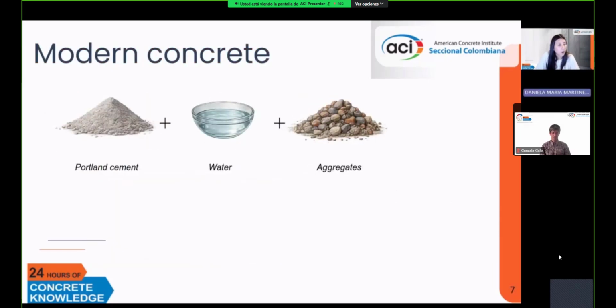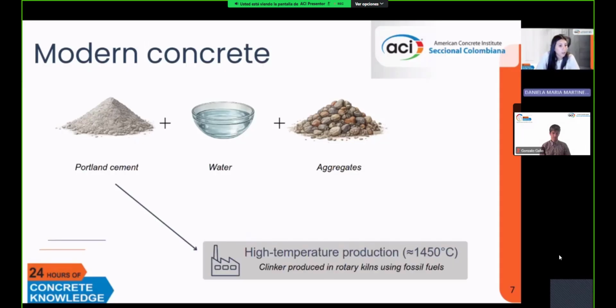In contrast, modern concrete consists of Portland cement mainly, and water that constitutes the mortar, and then we mix it with aggregates. In contrast with Roman mortars, the Portland cement needs to be first obtained with a mix of clinker and gypsum, and clinker is produced with much higher temperatures in our rotary kilns. These higher temperatures roughly reach 1,450 degrees Celsius. And unlike Romans, we have heavily relied on fossil fuels to be able to power these kilns to the temperatures that we need to reach in order to produce clinker.